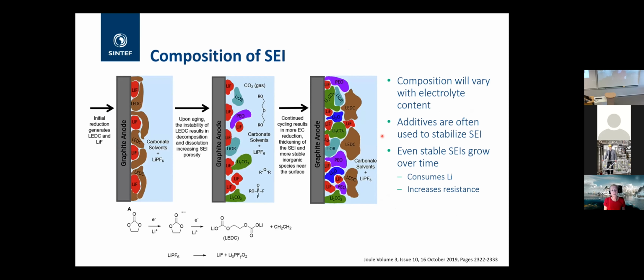If we look quickly at the composition of the SEI, it is probably one of the most studied parts of the lithium-ion battery, because it's extremely difficult to characterize and to get a grasp of. Obviously, first of all, it also changes depending on your electrolyte composition. We know that additives are often used to form stable SEIs, because the SEI is necessary to protect from further decomposition. So if you have a stable SEI, you have a first cycle decomposition, and then you prevent further deterioration of your electrolyte, or at least almost prevent, because no matter what you do, the SEI will grow over time and keep consuming lithium.